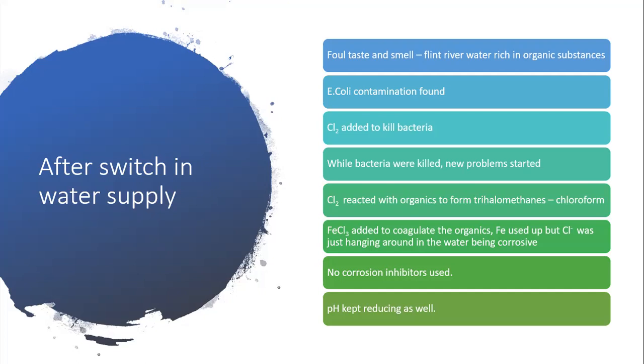To coagulate the excess of organic matter and prevent the formation of trihalomethanes, Flint added additional iron chloride. The ferric ions bind organic matter, but the chloride ions were hanging around in the water and they are corrosive, and no additional anti-corrosion measures were taken. Also, the pH of the water from the Flint water treatment plants was too low.